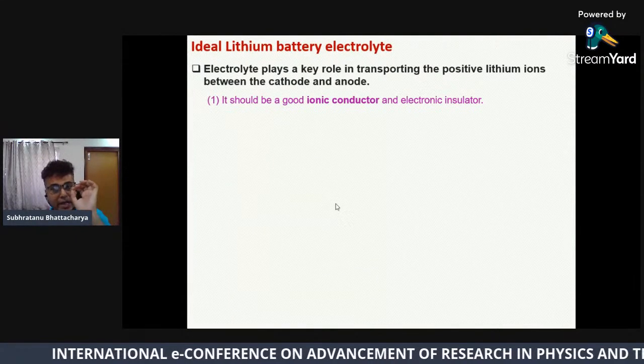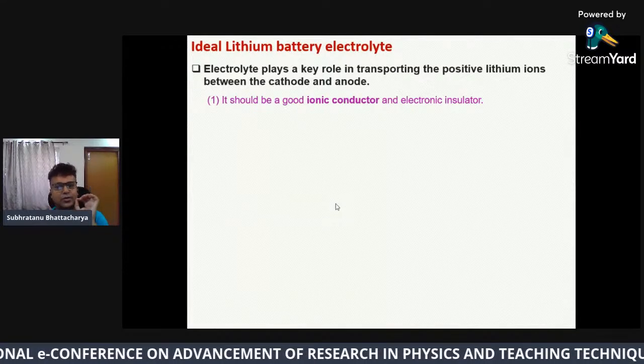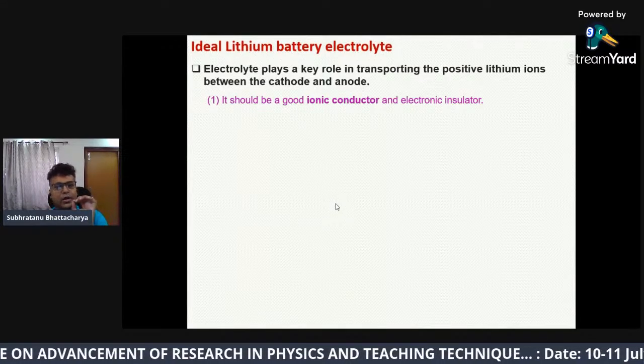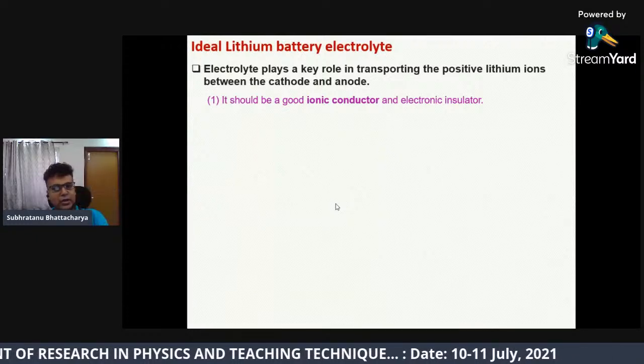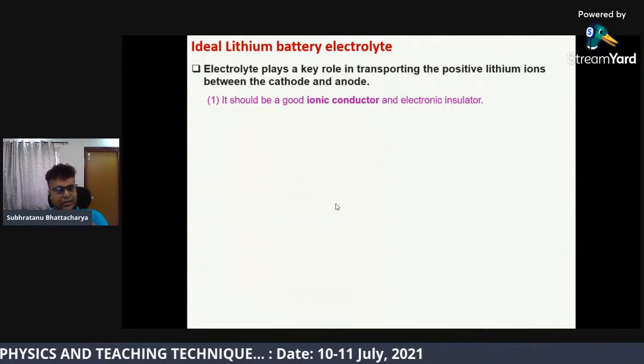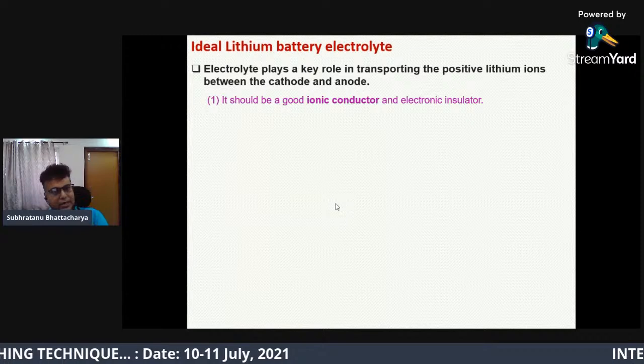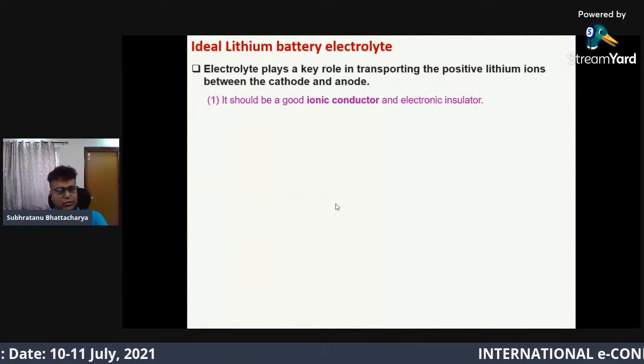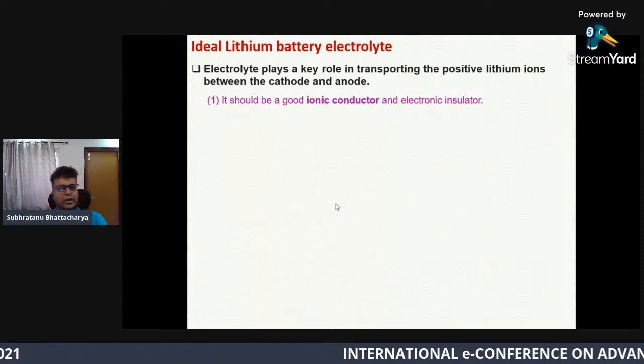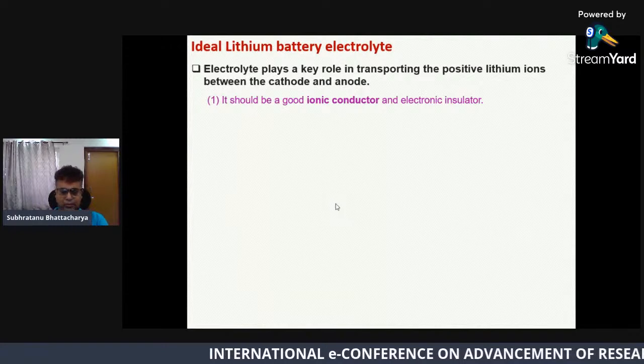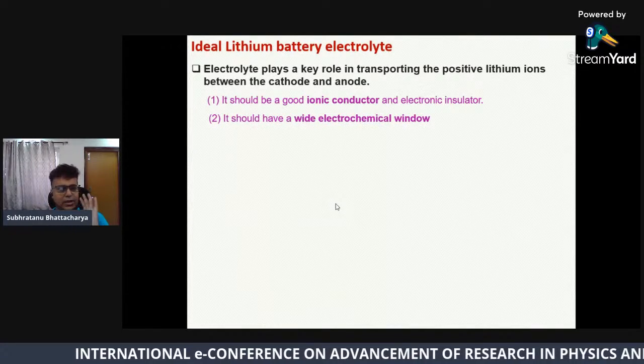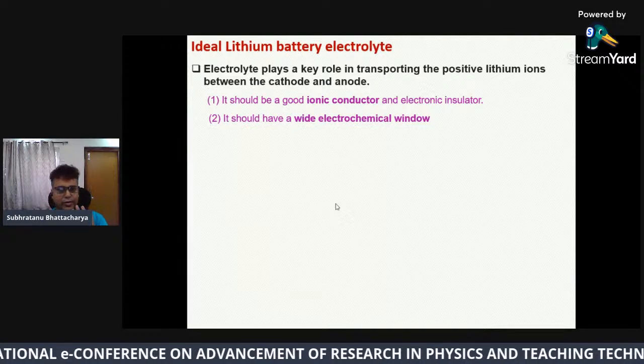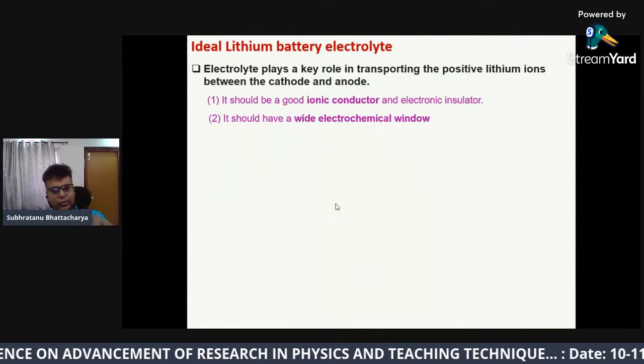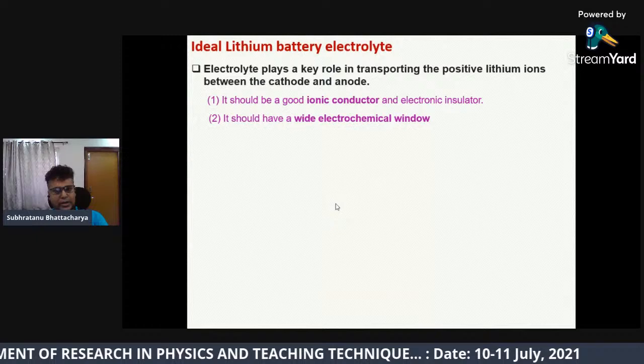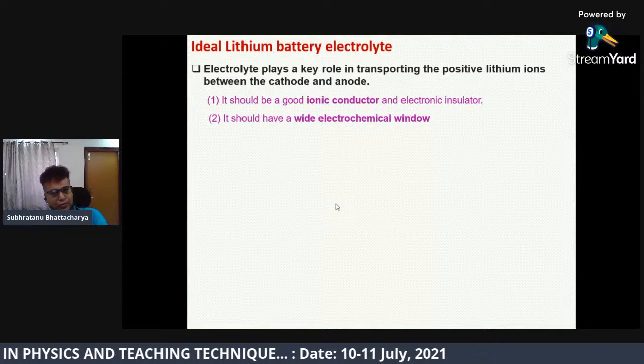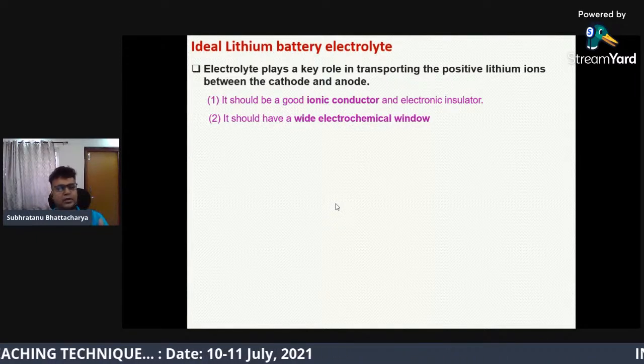So an ideal electrolyte should have these properties. It should be a good ionic conductor and electronic insulator. Means if it is also an electronic conductor, then electrons will attack the lithium ions, and you will get lithium metal instead of ions. So it should be totally an insulator for electronic conductivity. Next, it should have a wide electrochemical window. I have told you that we can charge up to 4 volt nowadays. If we can charge up to 5 volt, if we can charge up to 6 volt, then our energy density